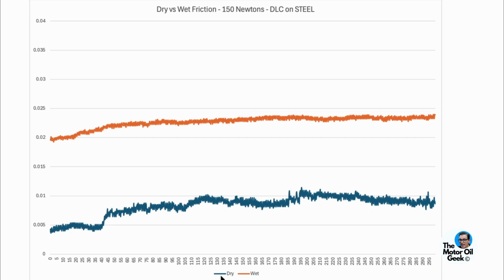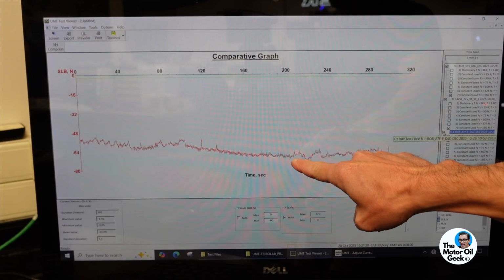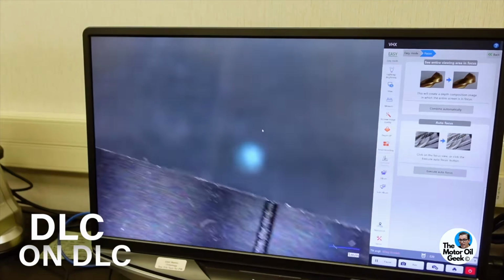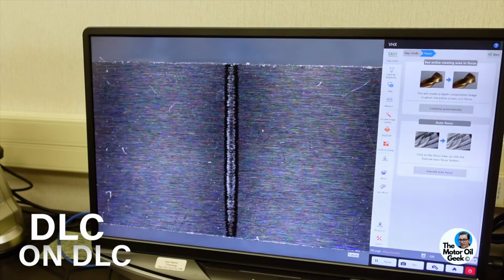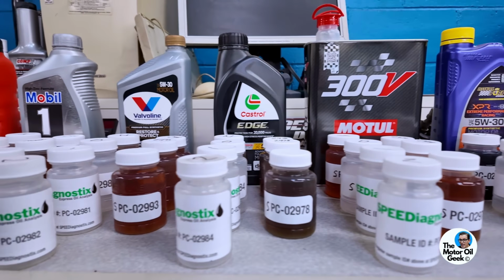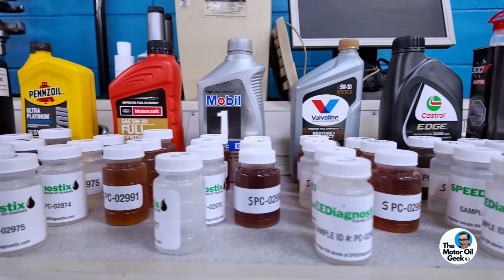From my NASCAR background, we knew that if you reduced the amount of oil you were putting on things when they were DLC coated, efficiency increased because you didn't have all the churning losses. Yes. But I would have never guessed that if you just took the lubricant away completely, the friction would drop like that. Kind of makes sense, but it's still quite a surprise that it's that dramatic. In a real application, it's going to be cooling as well. Absolutely. Oil isn't just a lubricant. It also cleans, it cools, it transfers power. It's got lots of other jobs to do, which makes motor oil interesting. But in this case, if you're trying to reduce friction, you're trying to reduce wear, DLC is